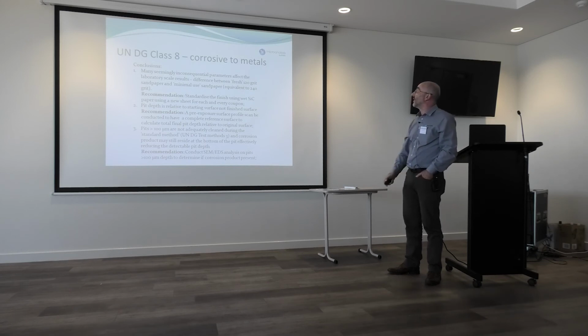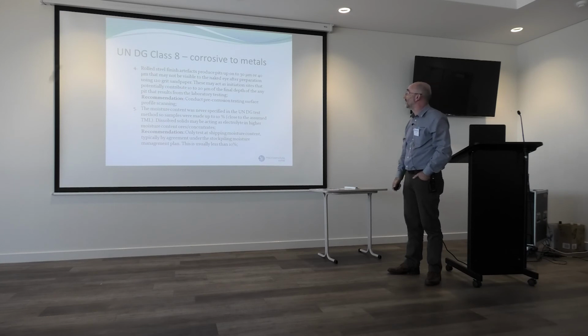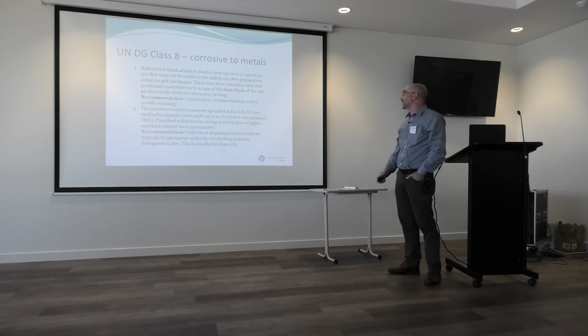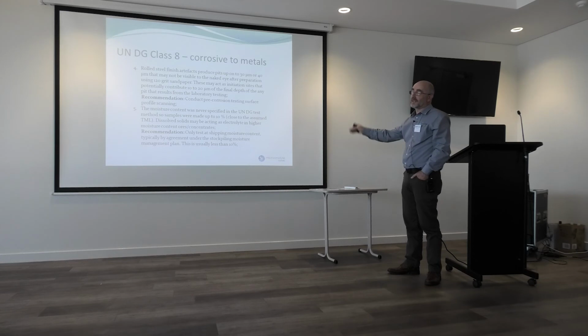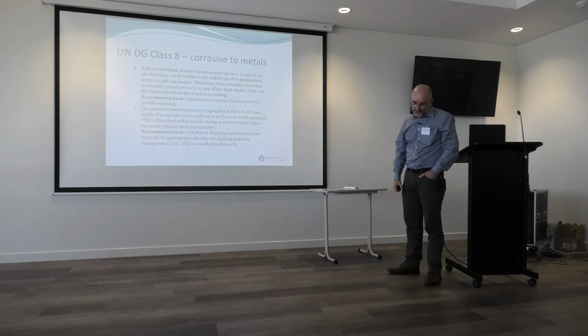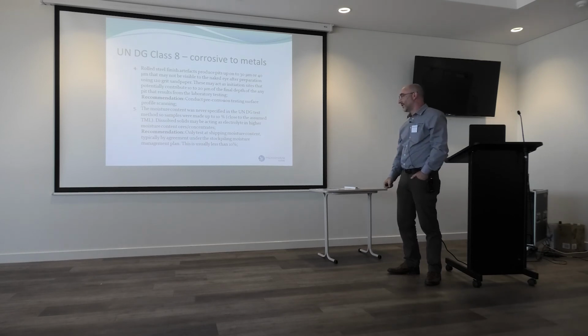So yeah, there's a whole range of things there that was brought out from some of the testing that we did. Probably the biggest thing was that the standard actually said that the moisture content was irrelevant, and there was a lot of talk between us and AMSA, which is the Maritime Safety Organisation, overly bureaucratic and never willing to make a decision. At the end of the day, they did actually say that all samples should be made up to 10%, but having said that, a lot of the samples that we're actually testing for the TML, if they're down at 7 or 8%, then if they're failing at 10%, it's a bit of an unfair test if it's never actually being shipped at that.